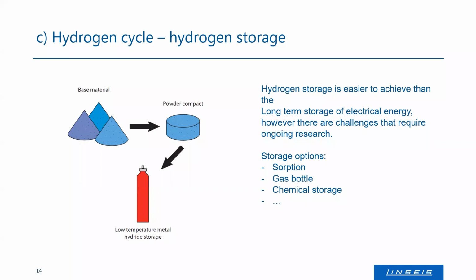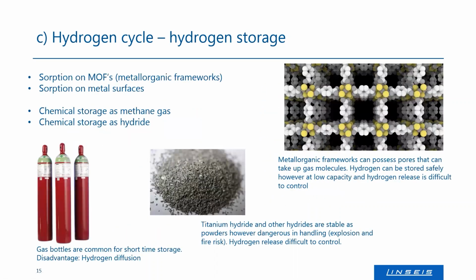The 3 ways you usually can do it: either you use an adsorber, so you can do sorption studies, sorption experiments, you can try to have a metal or metal mesh or other structures with micro or nanopores to do just sorption, so you can, either controlled by temperature or controlled by pressure, adsorb it and release it. You can use classical gas bottles and just press it with pressure into a bottle, or you can do chemical storage by having it react with some other elements or other molecules to form a hydrogen containing molecule that can release it back again, either thermally controlled or pressure controlled or chemically by a catalyst controlled. And even there, we have partners that do a lot of research.